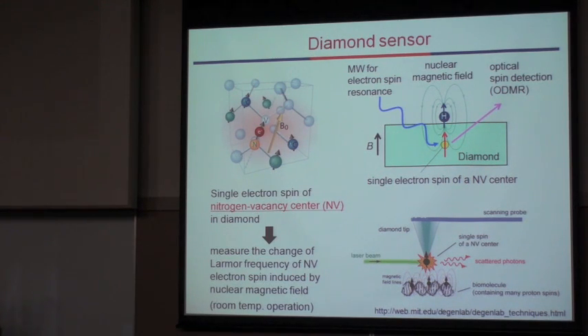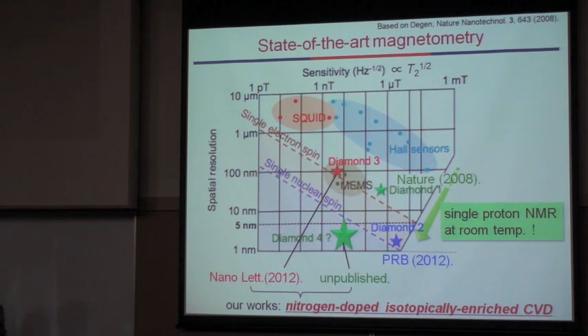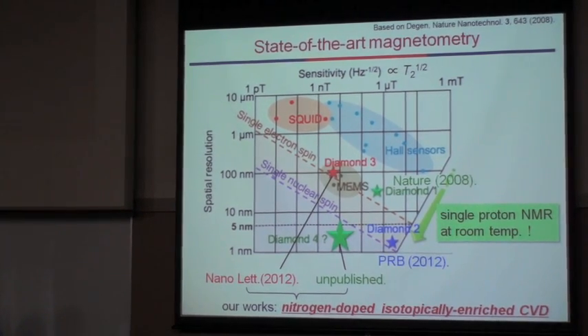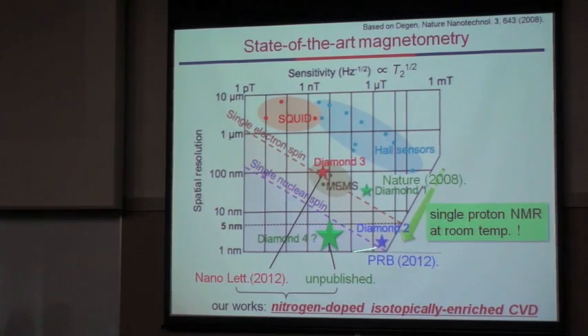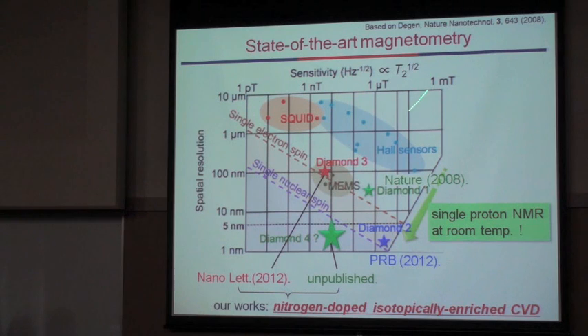This NV center has a lot of advantages. For example, NV center electron spin shows a very long coherence time, even at room temperature. This is very important to achieve very high sensitivity of magnetometry. Another advantage is that the NV center in diamond can be placed near the measuring target if we can dope the NV center near the surface of diamond substrate. As a result, the diamond magnetic sensor is expected to show higher performance compared to other magnetic sensors.